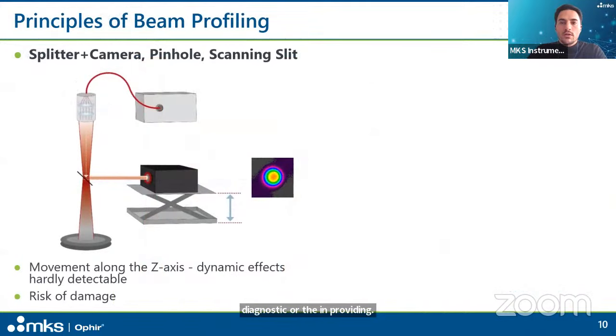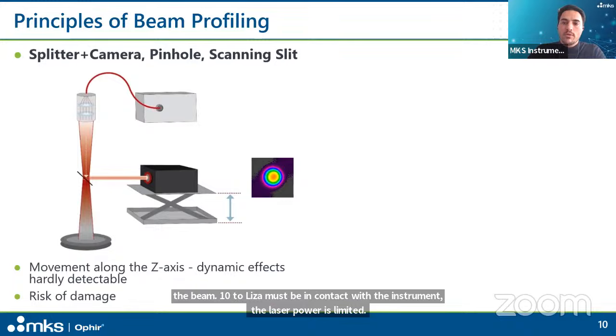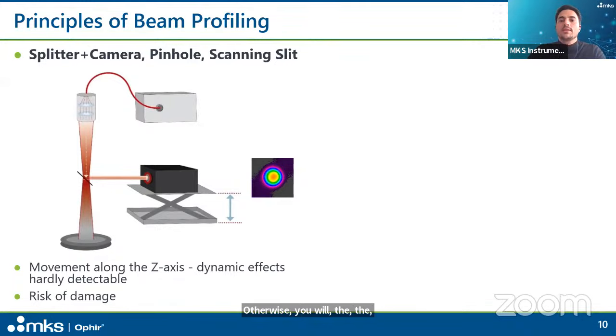There are two approaches to beam diagnostic. The first option, as you see here, is a beam splitter and a camera system, or a slit-based or a pinhole system. And these systems capture individual cross-sections of the beam. Since the laser must be in contact with the instrument, the laser power is limited. Otherwise, you will damage the measurement instrument. So it provides a detailed profile of the power distribution in the beam. And to measure the entire beam caustic, the measurement system must be moved along the z-axis and multiple cross-sections of the beam must be measured. This takes time, so dynamic effects such as the focus shift are not detectable.